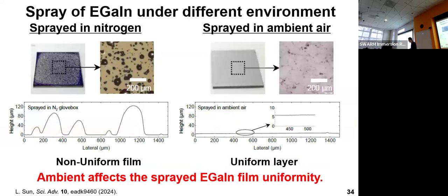And then an important finding is how to make uniform films of the EGaIn onto the active layer surfaces. Normally, the EGaIn liquid metal has non-wetting properties onto the active layer surfaces. But we found when we sprayed the EGaIn in ambient air conditions, we could make very uniform films onto the active layer surfaces, as you see here.